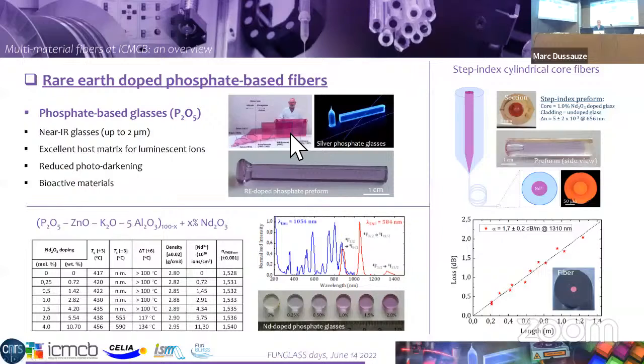Here, just these pictures. This is the laser mirror coming from the Laser Megajoule, used to generate high power lasers. Here is an example of homemade preforms and fibers, photosensitive preforms. And here is an example of a phosphate preform doped with neodymium. Here is an example of a study that we conducted in the past to develop phosphate fiber lasers. This study was conducted using neodymium, but we have conducted other studies with other rare earths like erbium or ytterbium, showing examples of doping into the glass matrix.